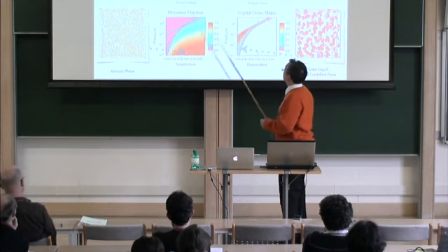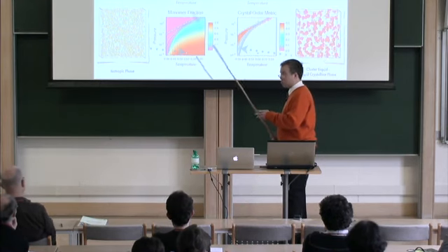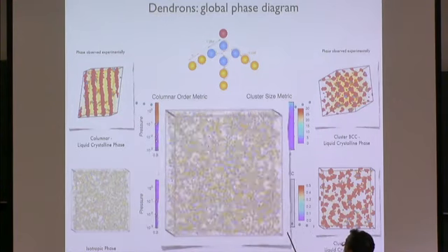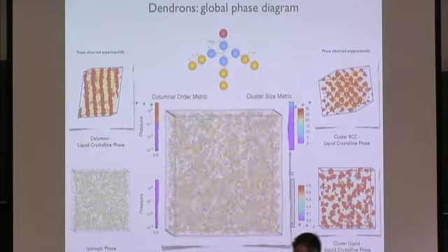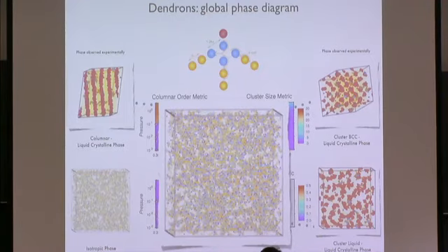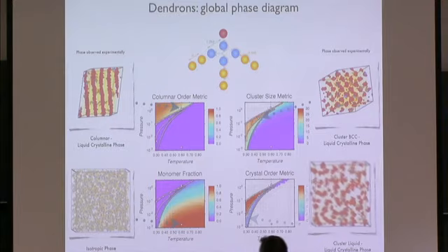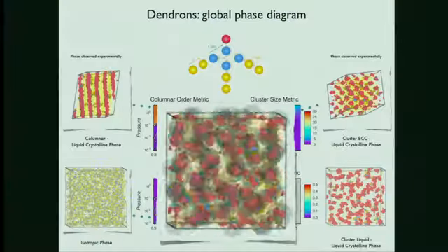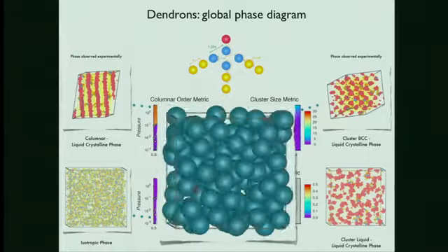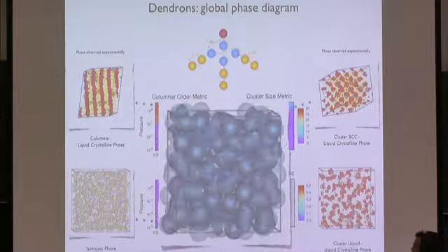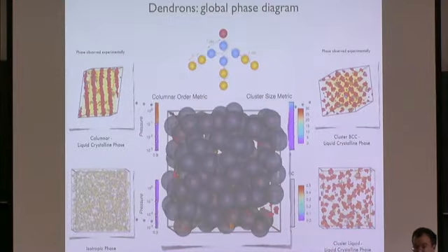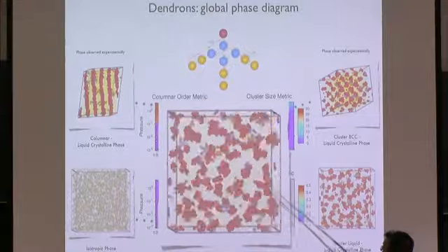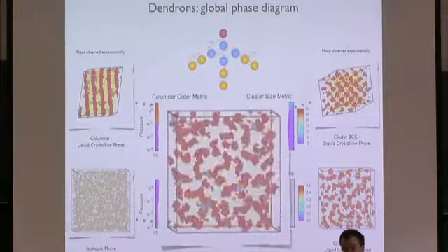So at the start, at high temperatures, we have an isotropic phase characterized, of course, by basically nothing. You just simply see that the system is completely isotropic. The moment you start lowering the temperature, you start seeing that the molecules have formed little clusters, and these clusters resemble that sphere I showed you. And if you follow the spheres in their movement, they look very much like a liquid. So we're talking not only about a liquid crystal in the sense that these molecules go from one of the spheres to the other, but we're also talking about a liquid from a supramolecular point of view.